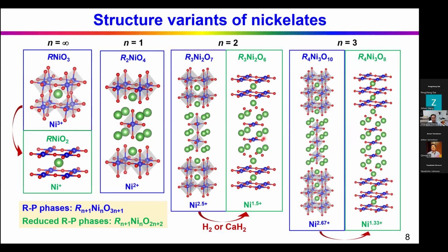So before I show the experimental progress, I will first describe the structures of the nickelate. Here are the reduced Ruddlesden-Popper phases with the general chemical formula of rare earth R(n+1) nickel Ni n oxygen O(2n+2). So this green phase actually has the square planar coordination and the nickel valence close to 1+. They satisfy this requirement of the proposal.